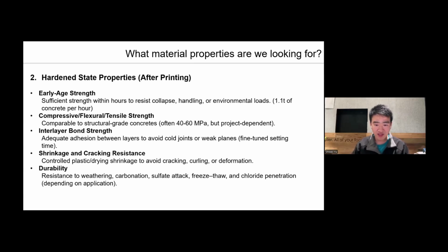And when printing continues the next day, we often use mechanical methods like nails or chemical bond agents to connect the fresh layer with the one we printed the last day. Then there's shrinkage and cracking. Without proper control, plastic and drying shrinkage can cause deformation or cracks. Because 3D printing mixes generally lack coarse aggregates, shrinkage control is very important for this mix.